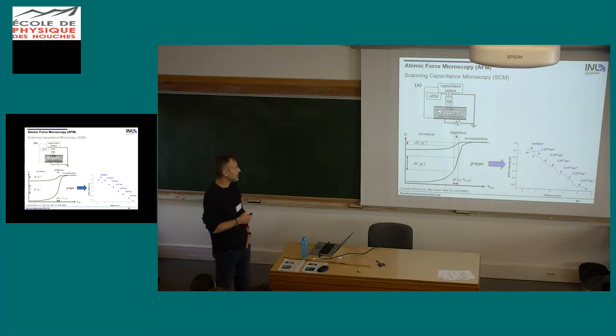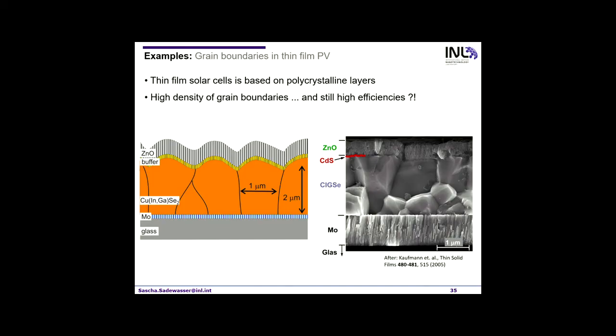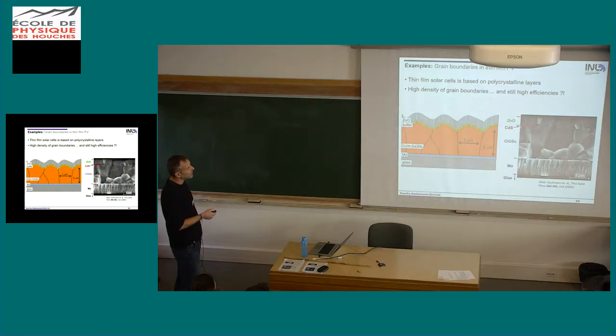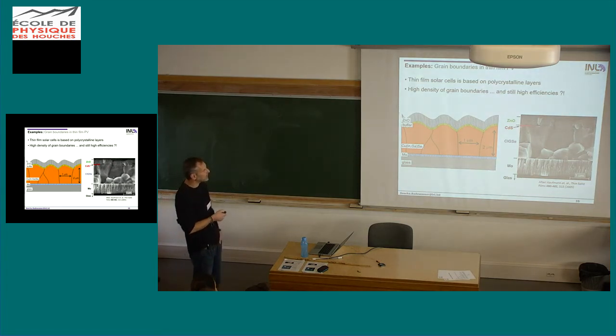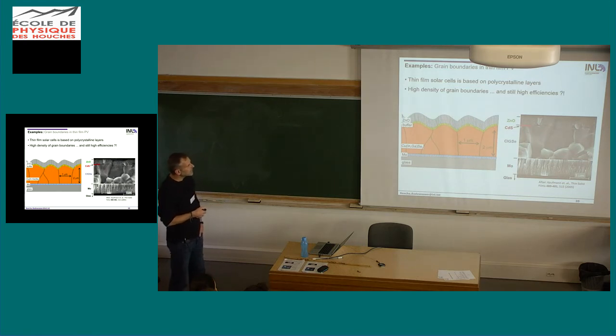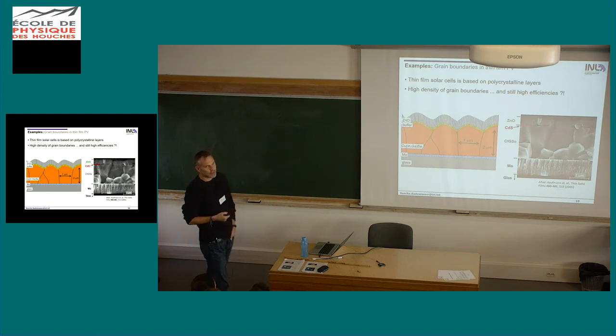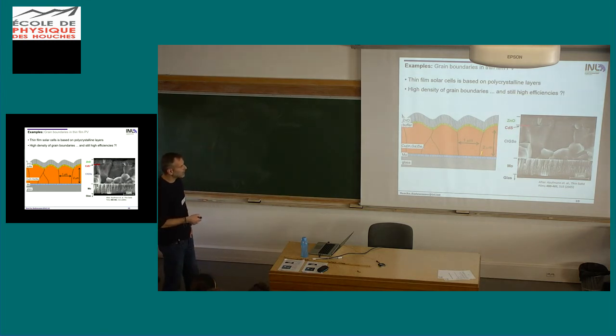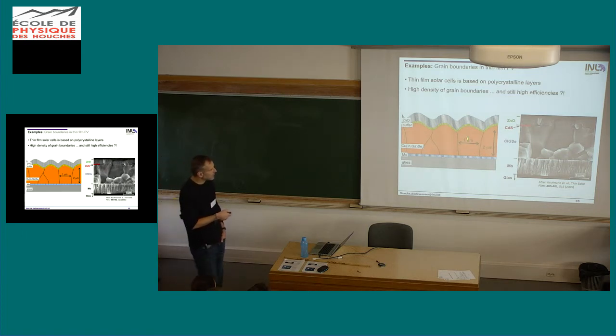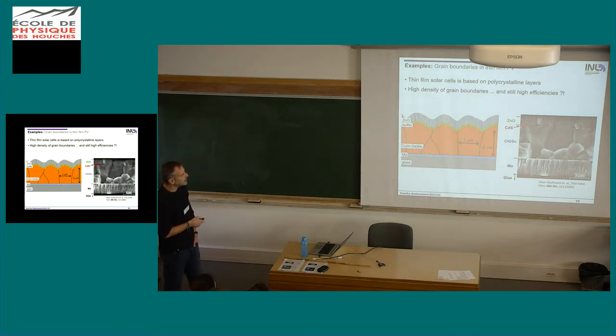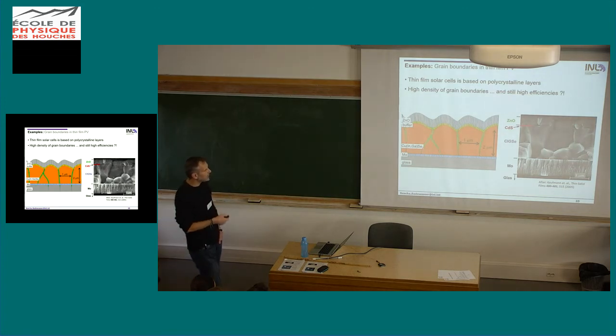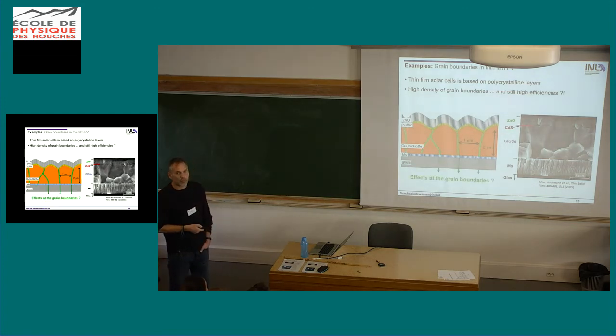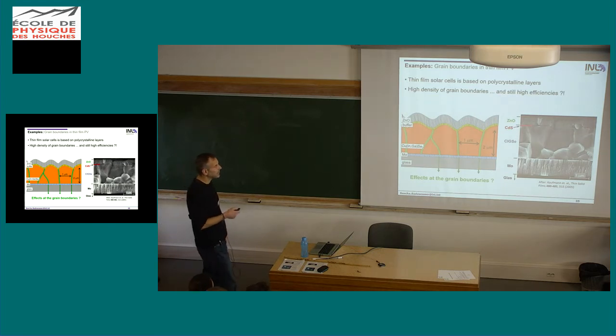So this has been applied, of course, also in solar cells. And I come back to what I said before, polycrystalline, so a quick intermediate introduction, polycrystalline layers. We saw something like this. So it's actually very surprising that these materials get to these high efficiencies, 23%. They have lots of grain boundaries, which normally are defects. We have grain boundaries in all these different layers. But of course, mostly we are interested in the CIGS material itself. So a lot of people have studied the effects and the role of grain boundaries to understand why these materials perform so nicely.